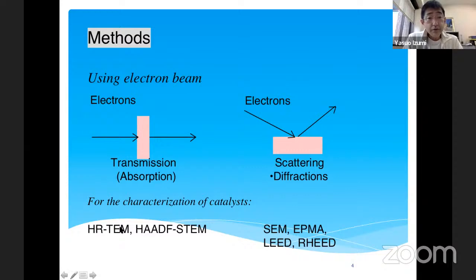But if you use HAADF-STEM, the image brightness of cobalt is 27 to the power of 2, and aluminum, if it is atomic, as a metal, the brightness is 13 to the power of 2. So the difference becomes much greater. And you can identify, for example, the cobalt nanoparticles existing among the sample. It's brighter using this. So by comparing these two, often you characterize.